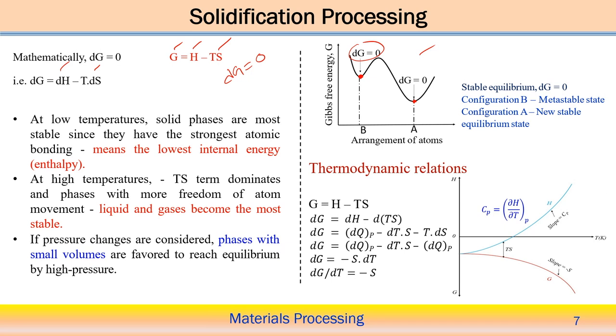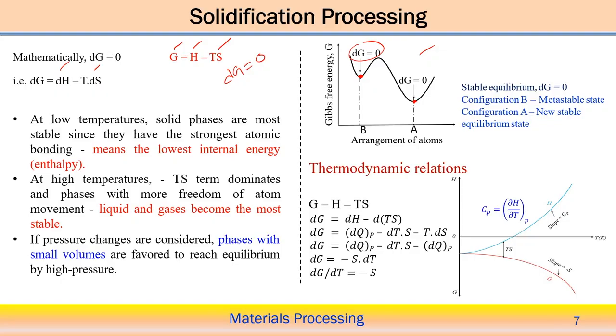So we mean to say that it might have several minimum points, and each minimum point where dG is equal to 0 indicates one particular configuration of the atoms, which will try to reach the equilibrium conditions. Therefore, a stable equilibrium condition indicates dG equal to 0. But configuration B can further reach another configuration of the atoms, A, which is more stable in this case. So configuration B is a metastable state compared to configuration A, which reaches another, most stable equilibrium state. Like that, it can reach several other stable equilibrium states, but mathematically it will always try to reach dG equal to 0. That means the change of the Gibbs energy should be 0, which always corresponds to the stable equilibrium condition.